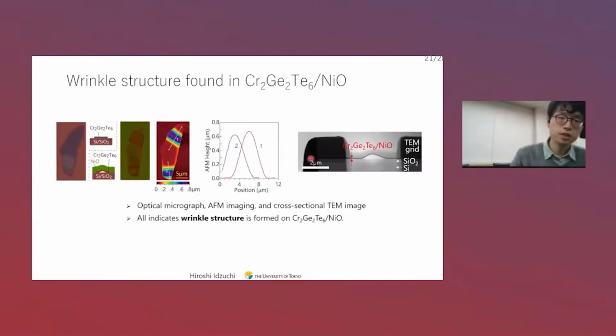This was rather incidentally observed, but before, we were studying CGT flakes with a nickel overlayer. And with the nickel overlayer, somehow we have additional optical contrast.